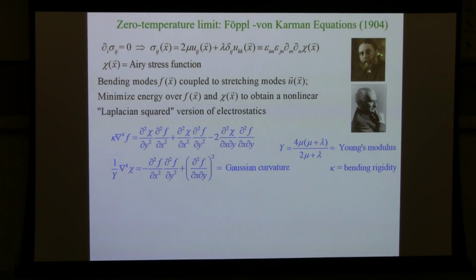Many of us think that Foeppl is kind of a doppelganger of Bert Halperin. It looks vaguely like him to me, my colleague. But take a look at these equations, right? They're nonlinear. And they involve chi and they involve F. The Young's modulus, that standard in-plane elastic parameter, comes in naturally, as does that bending rigidity, which controls the ability of these undulations to escape into the third dimension. And there's this nonlinear thing here, but there's also the Laplacian squared acting on chi with a source term over here in terms of F, which is nothing but the Gaussian curvature. So the Gaussian curvature of this elastically distorted membrane is acting like a source. It's kind of a Laplacian squared version of electrostatics here. And then there's a bilinear term in chi and F that comes into play.